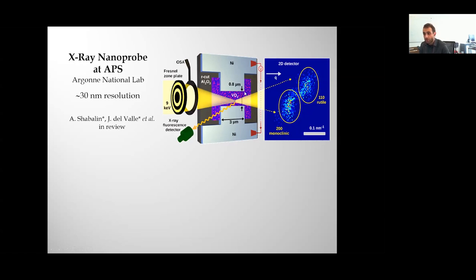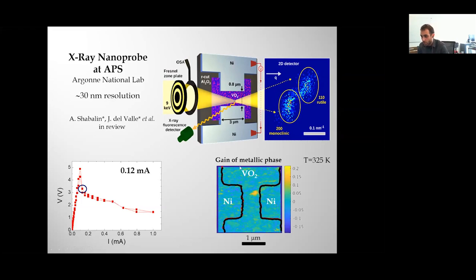So now if you raster this, if you scan this across all the field, you can make a 2D map of how much metal and how much insulator you have. And you can do that while you are performing resistive switching in this device. So this is what I'm going to show you here. This is a 2D map. You can see here in black line the nickel electrodes outline. So blue means more insulating, it's mostly insulating phase. Yellow means mostly metallic phase.